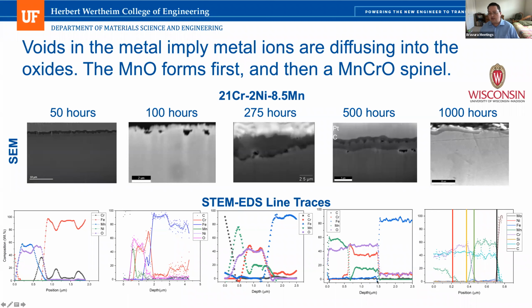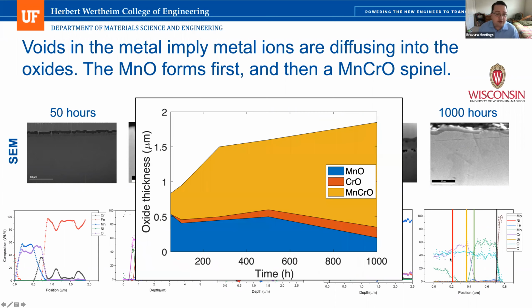And now this sample is just sort of done in reverse here at the 1,000 hours. This is our free surface, but we see the same general behavior. So we can go through and actually look at the thickness of the oxides over time. So at 50 hours, our manganese oxide is our largest oxide, but from then on, it's essentially shrinking, and we're getting less and less manganese oxide.